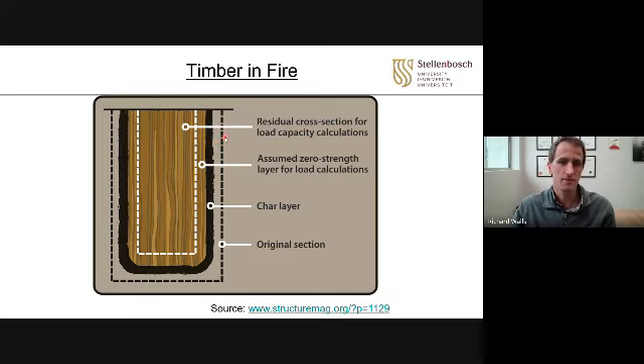So let's say after 40 minutes, you have 30 millimeters of char that has been eaten away. Then you also have a zero strength layer. It hasn't been charred, but it has been heated. Especially if it gets above 100 degrees Celsius, wood has moisture in it, and the moisture will be affected and the strength will drop. So you have a char layer, a zero strength layer, and then you have a residual capacity. Basically your dotted line is the residual cross section.